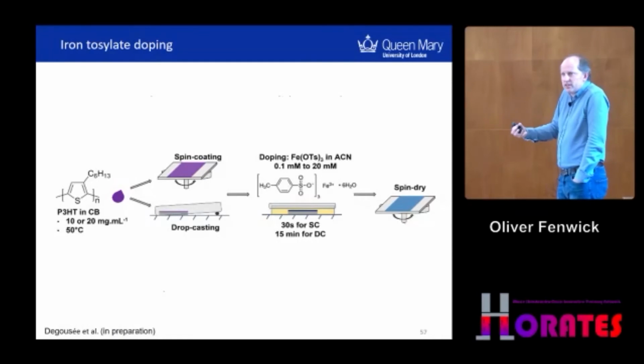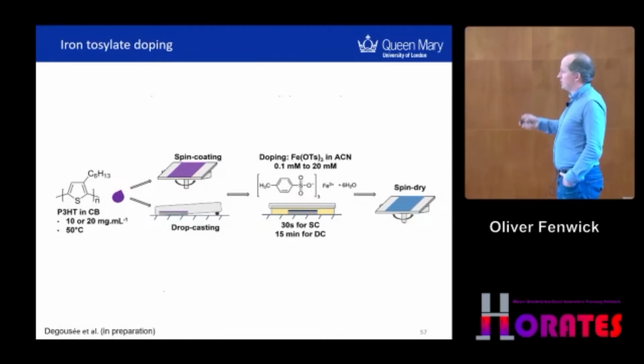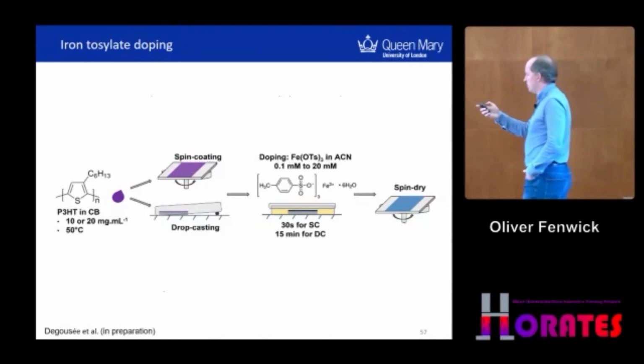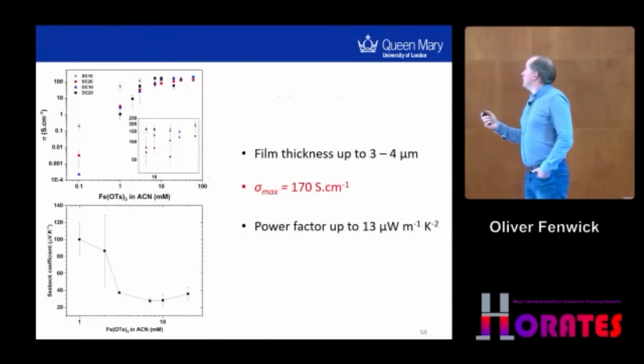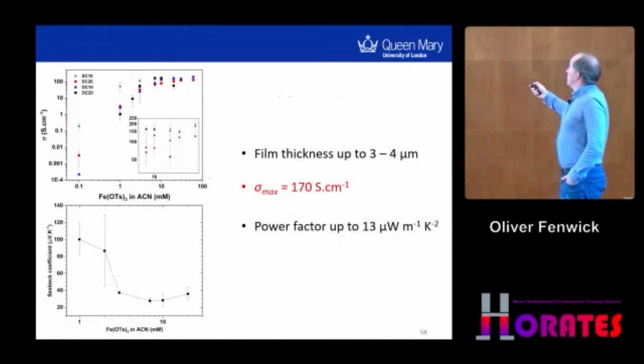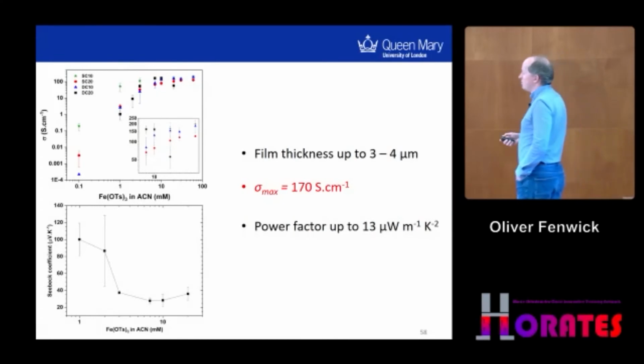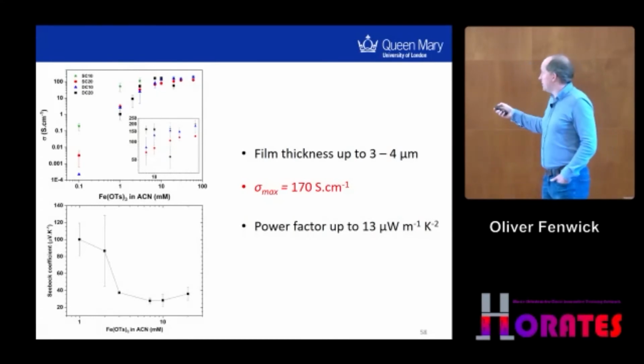Our motivation actually was to move to thicker films. Okay, so we wanted to move to micron thicknesses rather than 100 nanometers or less, which is what we looked at with the aligned films. And so we got films up to 3 or 4 microns, and when we dope, so there's a lot of data here. It's different spin-coated or drop-cast films with different concentrations. What we see is that they all reach a value of around 100 to 200 Siemens per centimeter, but specifically the thicker ones, 170 Siemens per centimeter, which is really rather high for P3HT.